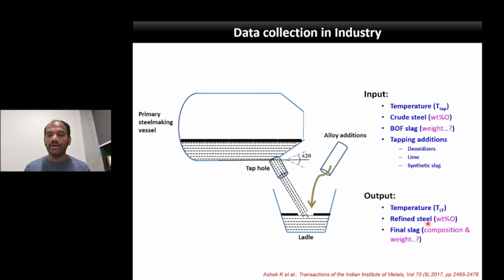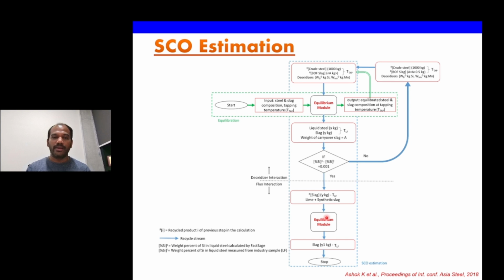That is the final temperature for our calculation in the equilibrium module. And the refined steel composition, including the weight percent oxygen, and the final slag composition and weight. So this is basically an input. The list of inputs, if you give in an equilibrium model, this list of outputs basically comes out through the equilibrium module of FactSage. And doing some exercise, one can calculate it; it's basically an equilibrium, and thermal and mass balance along with the chemical reactions. So one can perform this calculation and then estimate basically the slag carryover. I'll just explain in the next slide how that has been done.